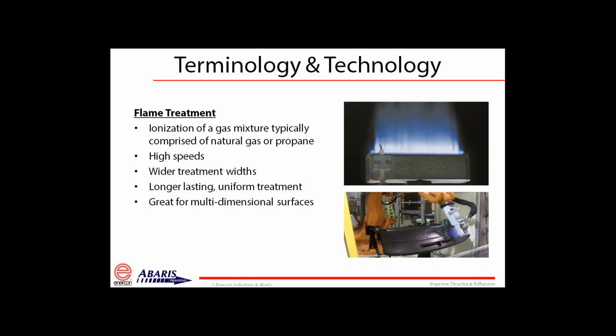What you see in the lower picture is a robotic application of flame treatment. We're treating the dash panel of a car, typically either before it would be painted or a foam applied and then leather wrapped. But what the flame treatment does is it allows an active area or treatment zone of about 2 to 3 inches tall, which allows you to really treat some parts with contour very easily. It tends to be processed very quickly and have a long-lasting and uniform effect on the surface.